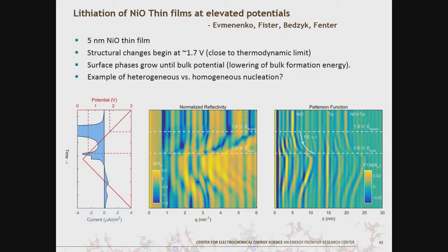I want to emphasize one point: if we look at the Patterson function, it's just the Fourier transform of the data. For crystallographers, it doesn't tell you the structure, but it tells you the interlayer spacings. The nice thing about that is you can see when things change. As we're dropping the potential down, not much is happening here.